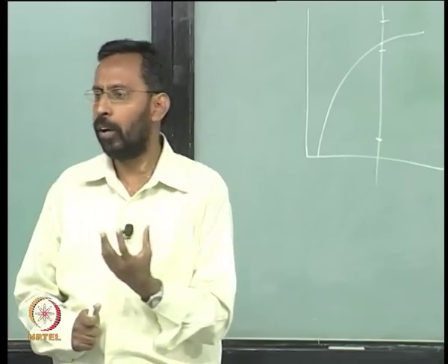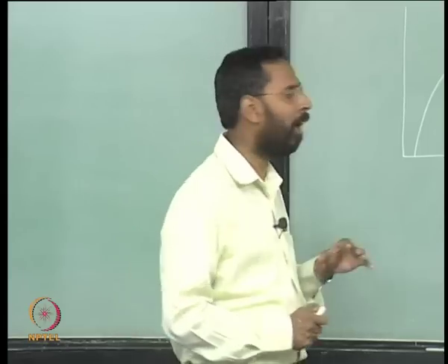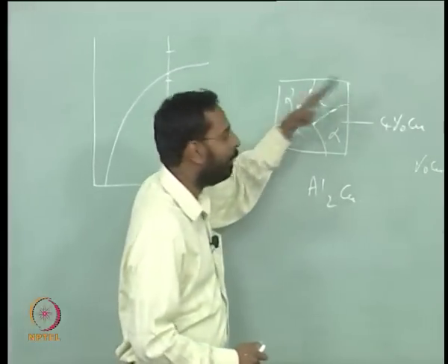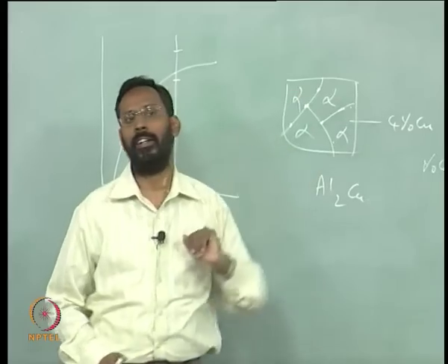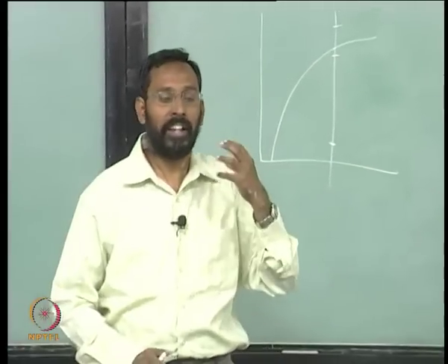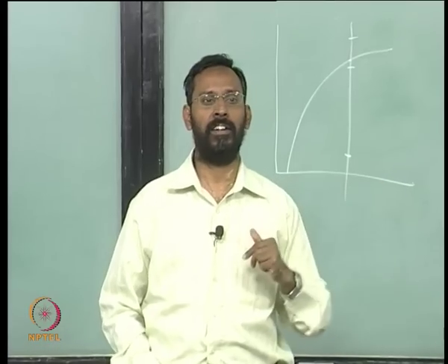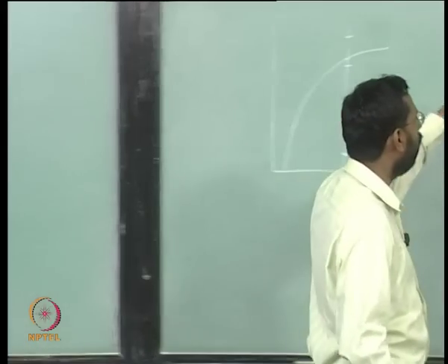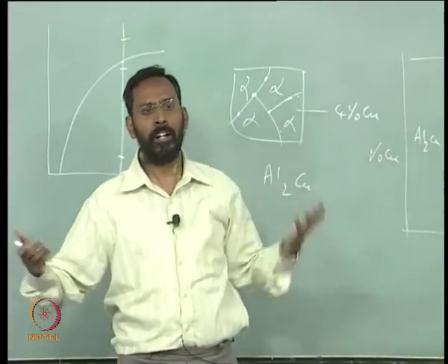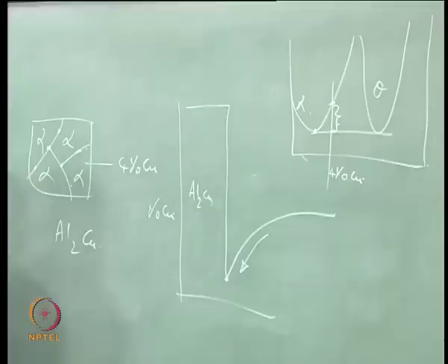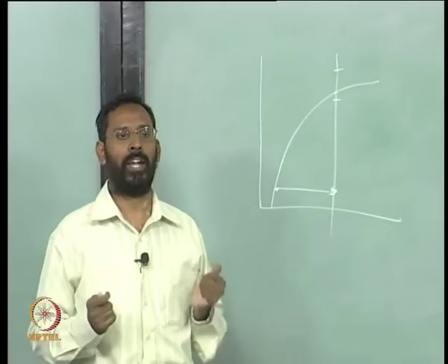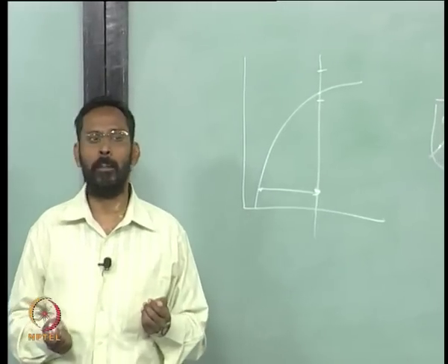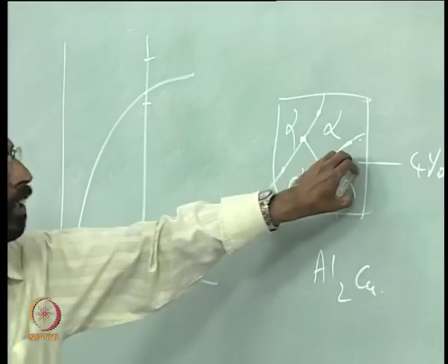So, the need for coherent nucleation comes into the picture because of the difficulty in nucleation at the grain boundaries and the necessity for nucleating within the grain. And where is the necessity coming from? Because it is supersaturated. It cannot remain as alpha anymore. Once you bring it to that temperature, this much supersaturation is not allowed. So, it wants to give away copper atoms. If it wants to give away copper atoms, then it has to nucleate within the grain, and if it has